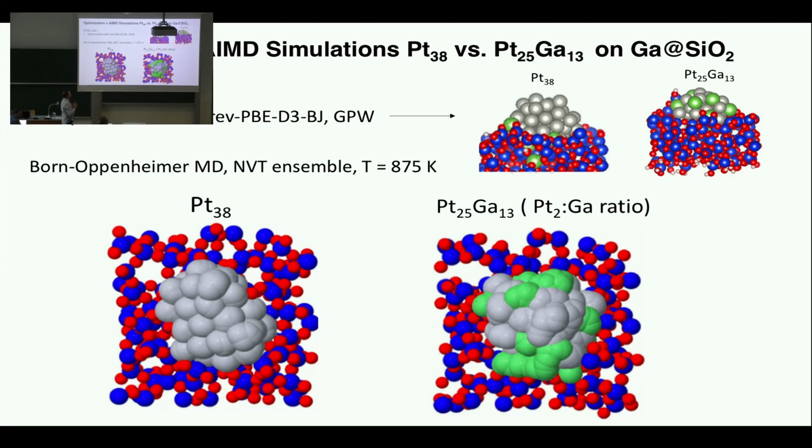Well, the way we understand, we think that at least for these particle sizes, which are also the ones that most resemble experiments, we see that this higher mobility isolates, in a way. There's another aspect here: platinum steps maybe form more easily on this kind of system, or steps, one could say, more saturated. And the other aspect is that propane doesn't like gallium at all. Propane wants to interact with platinum rather than with gallium. From one side you have this higher mobility in here than in there, and from the other side you have propane that wants to react only with platinum, not with gallium. These two things we think are behind the higher activity on this system than on the other one.